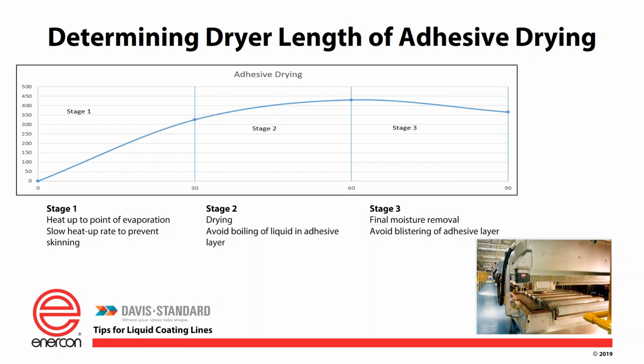Okay, so stage 2 is where I have very little evaporative cooling, but I still have moisture to get rid of. And then stage 3 is where I do my final drying. So if I'm going to get, let's say, from 5% down to 1%, at this point I have no evaporative cooling, but I've got to get those moistures out, and I can't boil the coating that's there. It'll blister in a different form, whereas in stage 1 it creates a skin when it boils first. Over here I'm boiling this almost a solid, which creates craters. So stage 3 is where I'm trying to get the final out at a different temperature level.